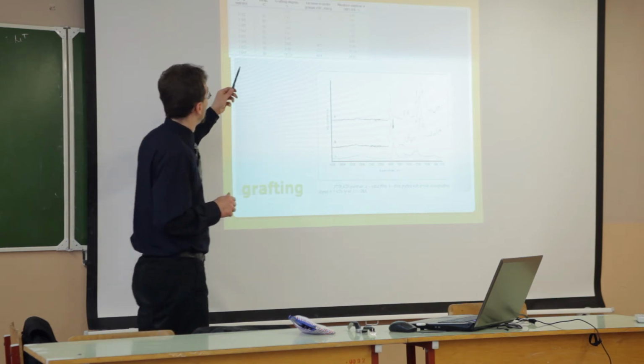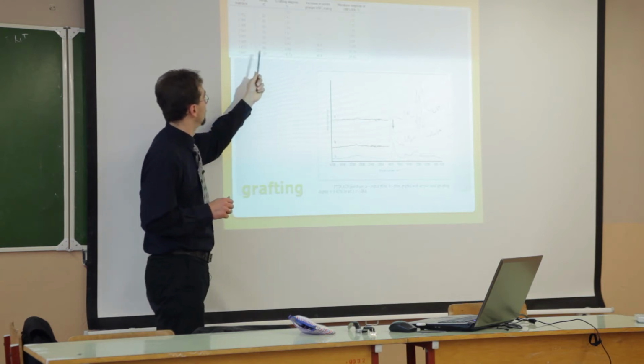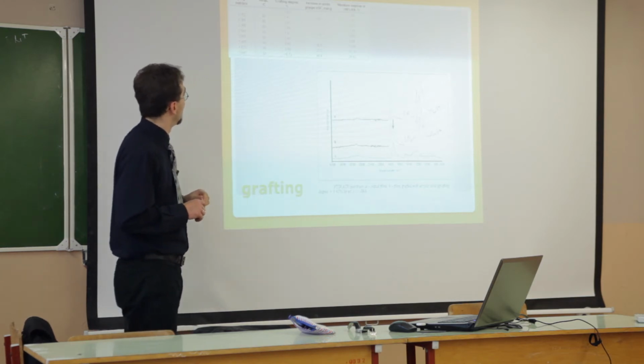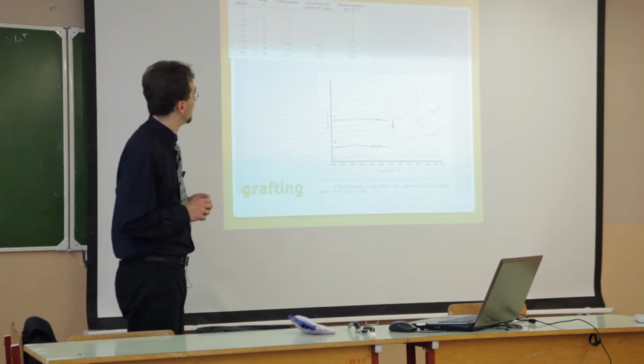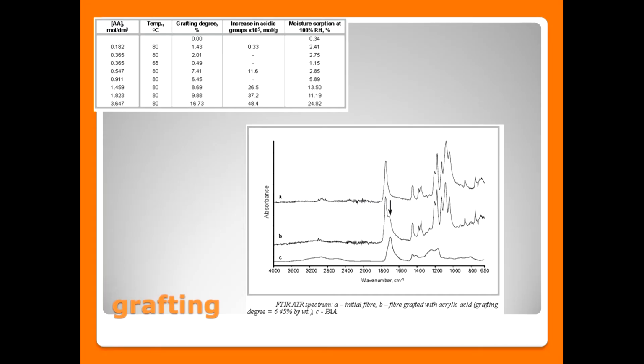We have to use temperatures close to 80 degrees, and it takes 1-2 hours, so it's not an easy process. The number of acidic groups on the surface was too small for us, so how can we control the structure?